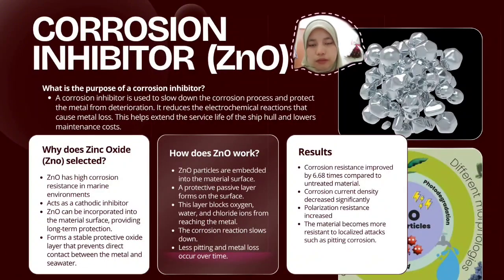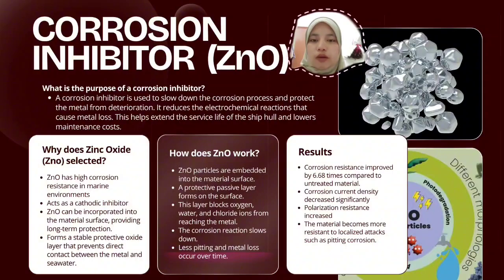Let's continue to the corrosion inhibitor selection. For the corrosion inhibitor selection, we choose zinc oxide because it has excellent corrosion resistance in marine environments. Zinc oxide acts as a cathodic inhibitor and can be incorporated into the material surface to provide long-term protection. When exposed to the environment, zinc oxide forms a stable protective oxide layer on the metal surface. This layer acts as a barrier that prevents oxygen, water, and chloride ions from reaching the metal. As a result, the corrosion reaction is slowed down, reducing pitting corrosion and material loss. In addition, the results showed that zinc oxide improved corrosion resistance by approximately 6.68 times, making it an effective and reliable corrosion inhibitor for ship hull applications.